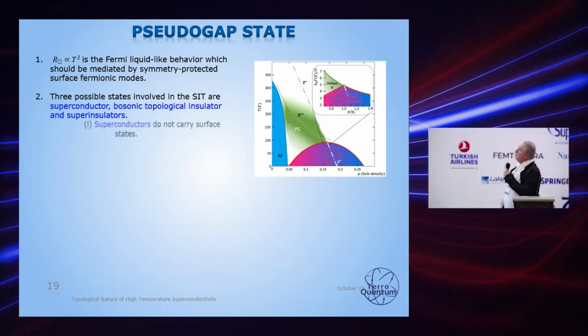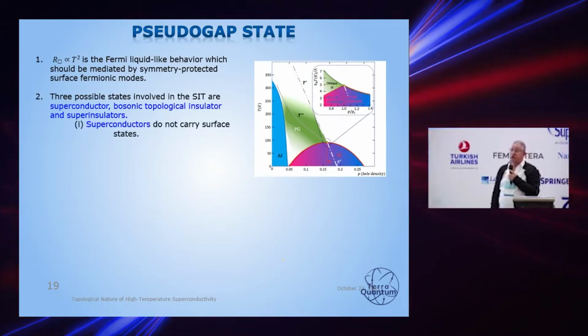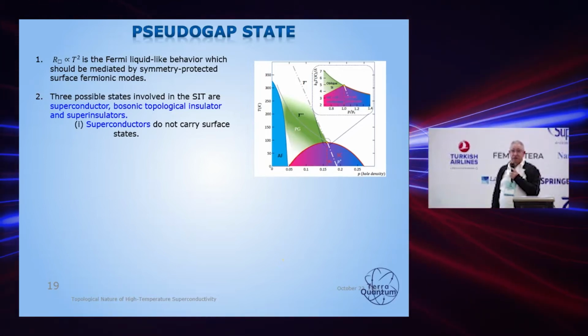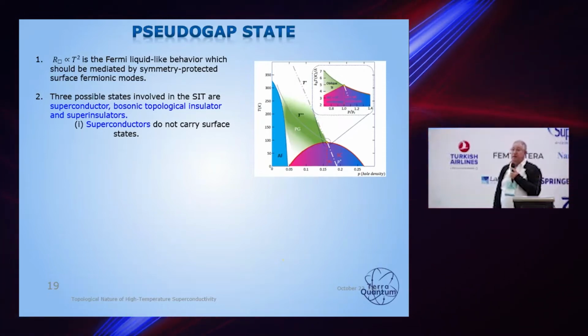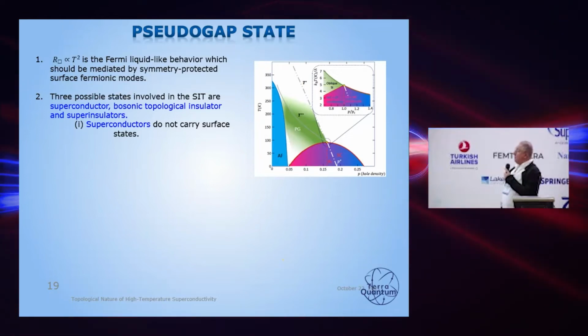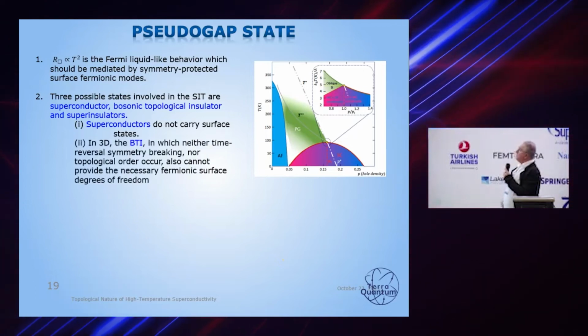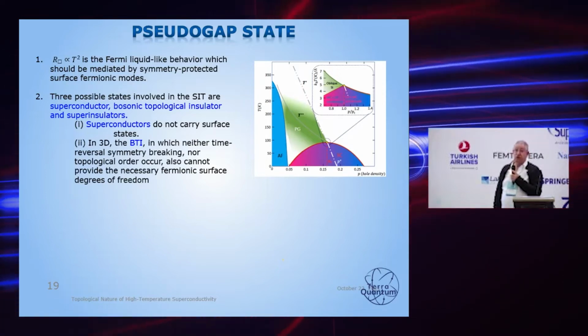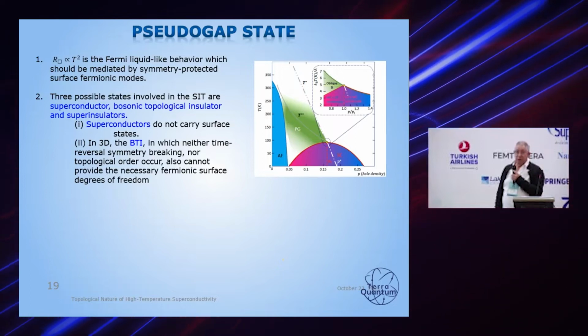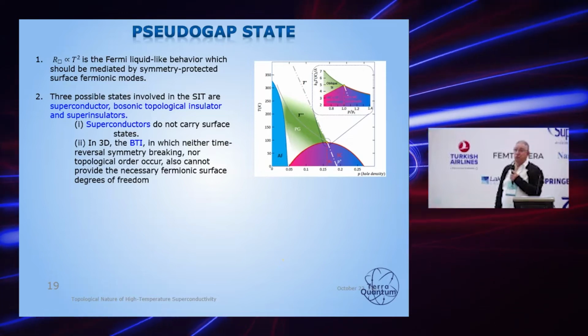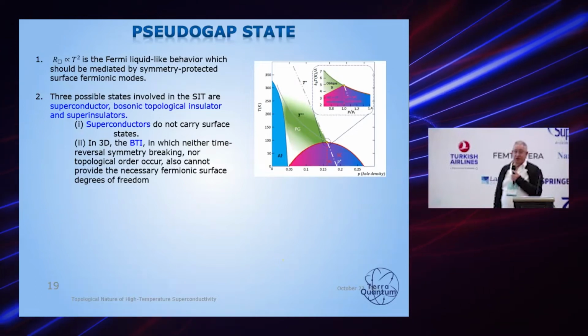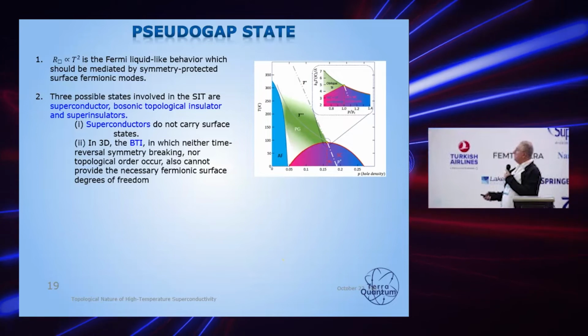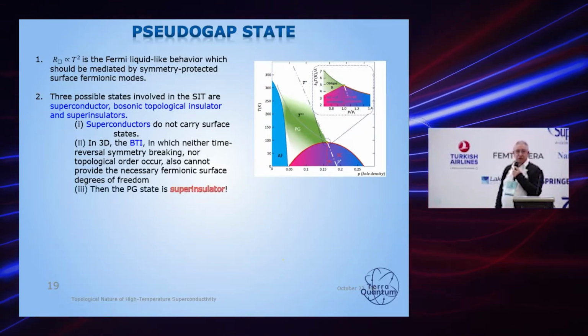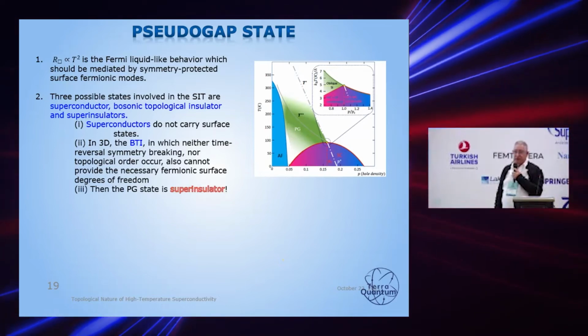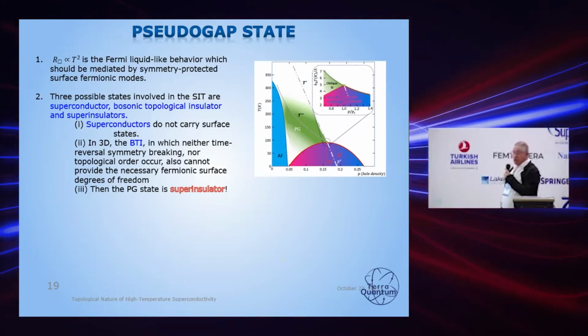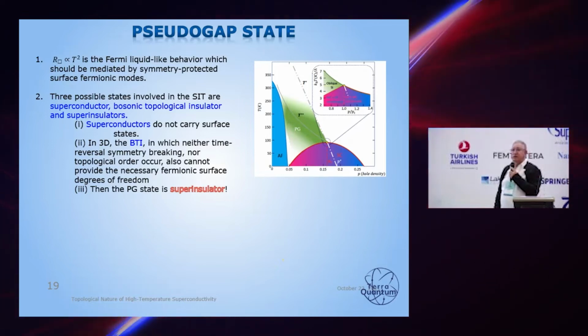Now, the possible states we know that can appear near the superconductor-insulator transition, and remember we decided that it is the superconductor-to-insulator transition which dominates the high-Tc behavior. The first phase which appears there is superconductors. They don't carry any surface states, so it doesn't work. Then there is the topological insulator. It also doesn't have any topological bound or surface states. So this phase also doesn't work as a candidate which can describe the pseudogap state. Then the only state which remains is the superinsulating state, which looks absolutely counterintuitive, because what can the superinsulating state do at this elevated temperature? Well, it looks like that.